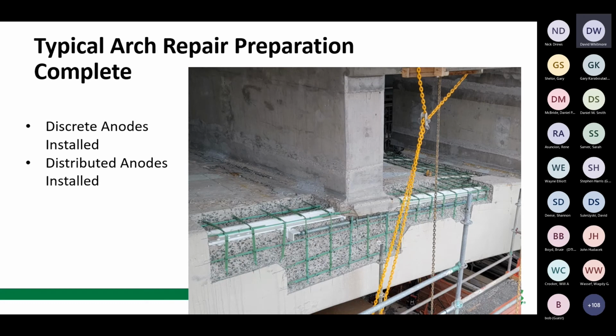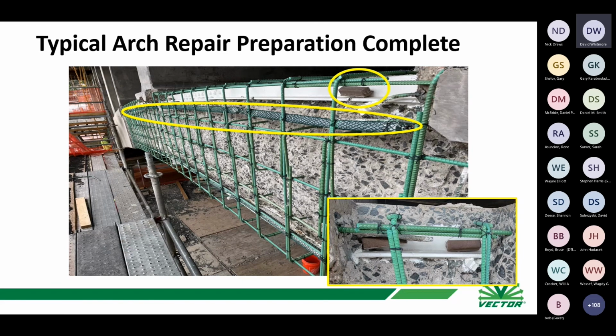Here's the same thing, but you can see the anodes are installed. You can see the distributed anode installed underneath the Melan angle going along there, and you can see discrete anodes at the 2 ends, and I think it's more clearly shown here. So here you can see all of the steels installed. The distributed anode is just underneath the Melan angle at the top, and there's a similar one at the bottom because this is a whole face repair. And then at the ends of the repairs, you can see the discrete anodes.